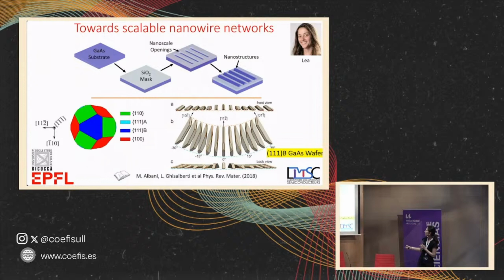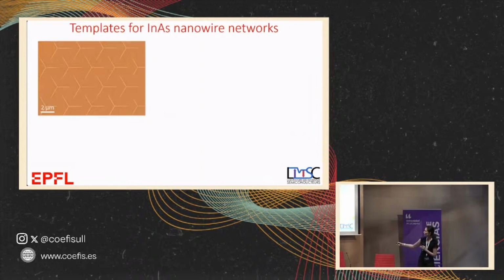And this is then the equivalent of 1, 1, minus 2. And there are 3 of these in 1, 1, 1 substrates. So this allows us to make these tripods here that are made of gallium arsenide. Now, gallium arsenide is not the material we want, and I will tell you later on why. But it is the base to create something on top.